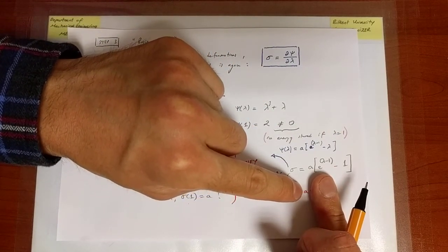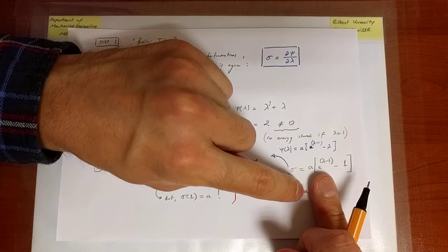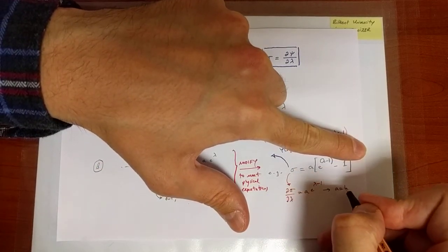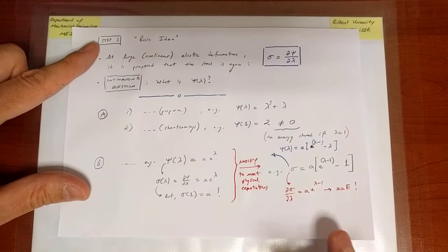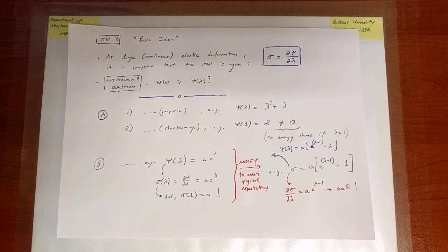But I know that the stress-strain relation is linear and the slope is E at small deformations, and we conclude eventually that A is supposed to be equal to the Young's modulus. This is again a physical requirement that you would actually come up with yourselves in our in-class discussion. So what you've just invented, by the way, is very intimately related to something called the Fung model. It's one of the famous initial models of biomechanics for soft tissue.